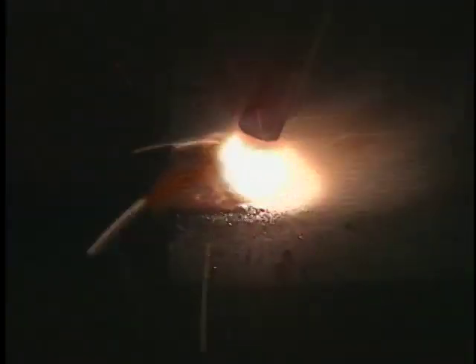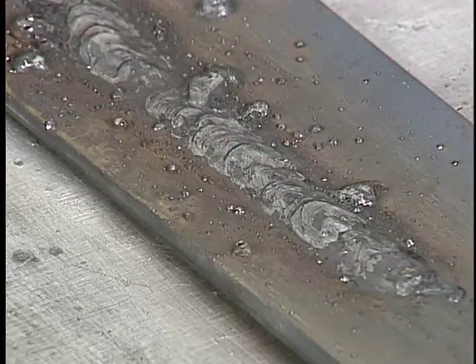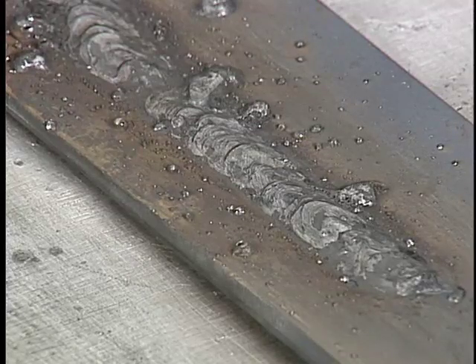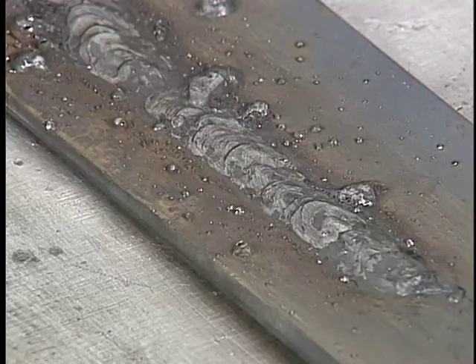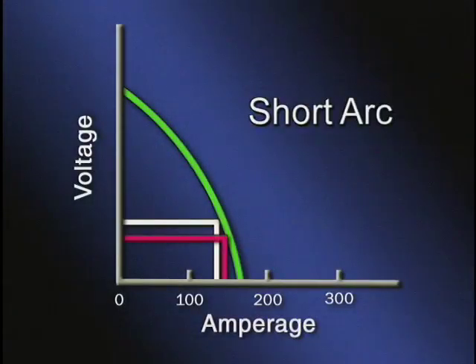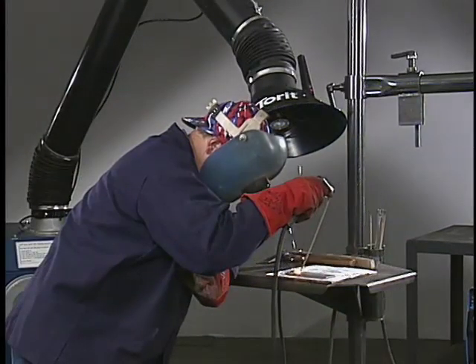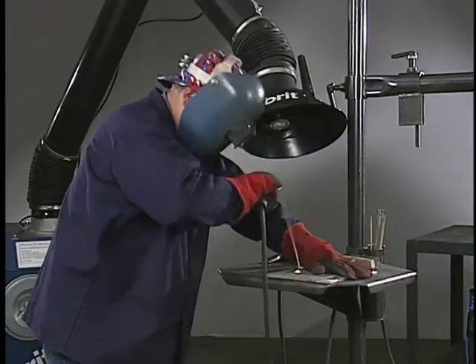If the arc is too long, the metal core melts off in large globules that wobble from side to side and drop onto the work as spatter rather than forming useful weld metal. The weld bead is wide with excessive spatter and undercut. The base metal is not properly melted, so the weld metal is deposited on top of the plate with incomplete penetration, and slag inclusions may occur. Long arcing is often used to preheat the base metal directly after striking the arc. Shortening the arc length reduces the arc voltage and increases the amperage slightly. If the arc length is too short, the arc has a tendency to short out and the electrode freezes to the work.